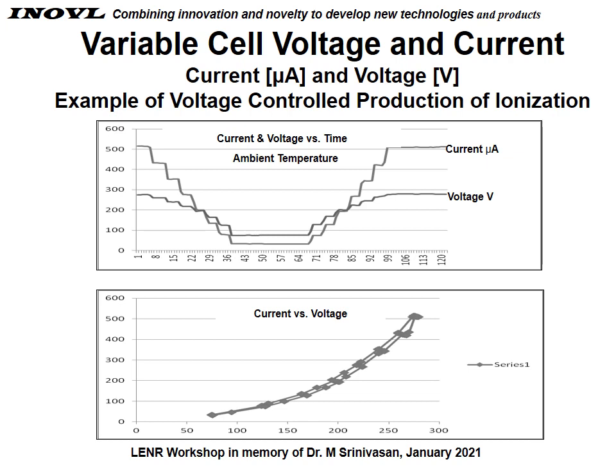This slide shows the test that was conducted at point B on the previous slide. In one of these tests, we would reduce the voltage in steps of typically 50 volts or so, and monitor the current as it comes down. And so here you see the voltage is on the lower trace, the current is coming down on the upper trace, and then we go back up and everything responds pretty nicely. Down below is a plot of current versus voltage, and you see one of those plots is coming down and the other plot is going up.